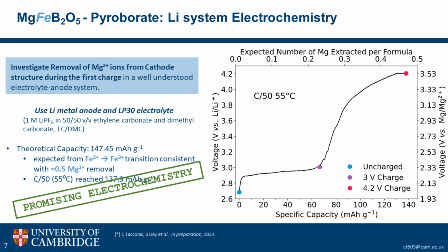What we see is that we reached almost 100% of our theoretical capacity. And we have this really nice promising electrochemical curve that we would expect to get from a transition of all the iron 2 to 3+ in our material and a removal of about half of the magnesium from the cathode structure. Just to note that the batteries are cycled at C/50 and in an oven, just to help with the slow dynamics of the magnesium.